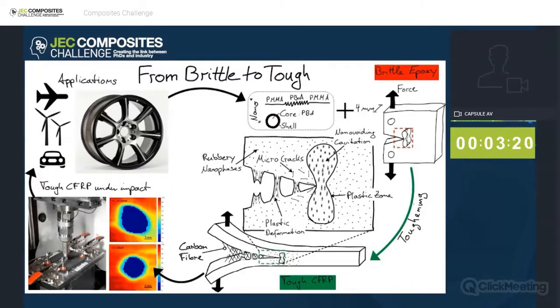So the third approach is to put obstacles into the material, obstacles that can stop the crack, or that the crack needs to interact with, which dissipates energy in a certain way. You can either do that with rubber particles, but rubber particles will usually decrease your glass transition temperature, and that is a problem if your rim is closely located to the braking system. On the other hand, you can use stiff, rigid particles, for example, but they will need a lot of energy-intensive dispersion efforts. So my approach is focusing on self-assembling macromolecules.